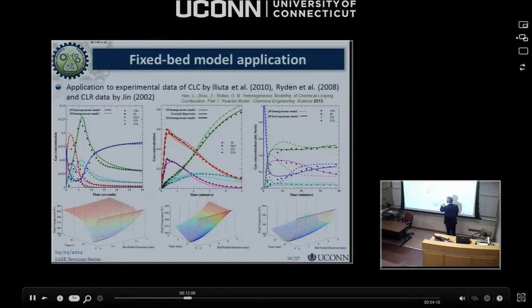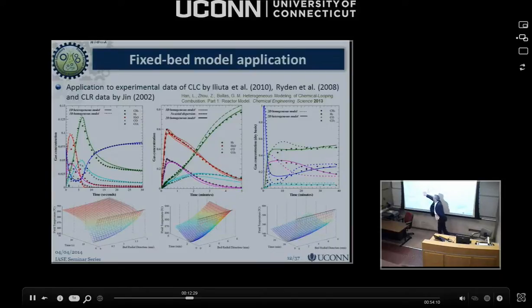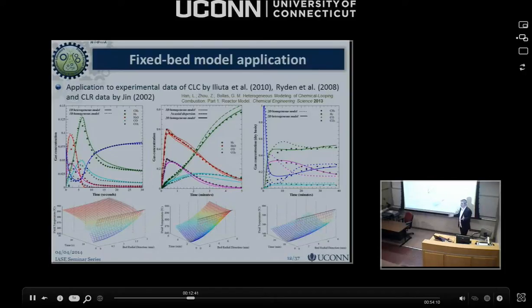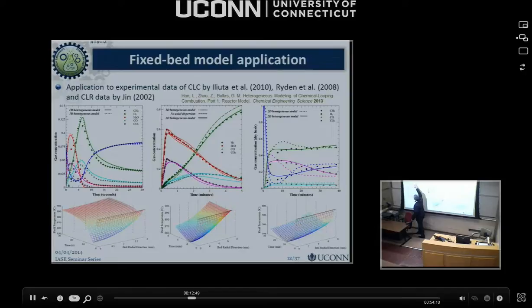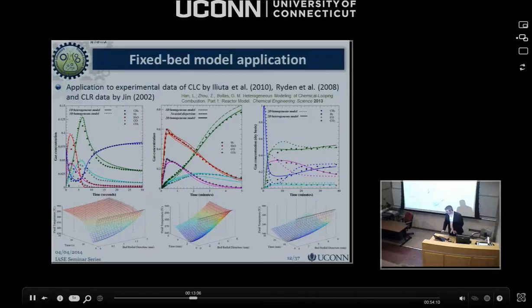To prove the validity of our models, we utilized published data from a group in Canada, a group in Sweden, and a group in Japan — for chemical looping combustion with methane and nickel oxide — and also chemical looping reforming, a slightly different concept where you also add water to produce hydrogen. With the same model and the same kinetic constants and kinetic network, we accurately simulated all the experiments available. A typical plot shows gas concentration versus time for a fixed bed reactor — by definition a transient experiment — where you get high CO2 in the beginning, then it drops down as the nickel oxide is being reduced.